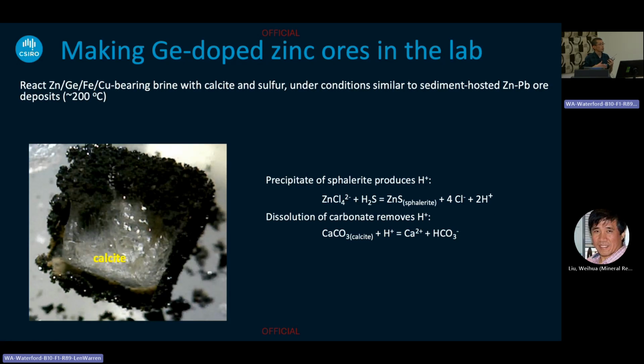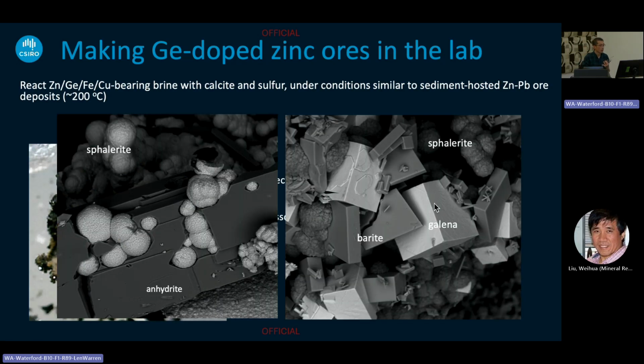But this is not good, because to make sphalerite stable, you want to remove the hydrogen from the system to make a better ore fluid. So that's why we have calcite there. Calcite will neutralize hydrogen and release calcium. But really, the key is when you have calcite and those fluids together, the calcite helps to drive the first reaction this way. You're going to expect more sphalerite to accumulate in the rock.